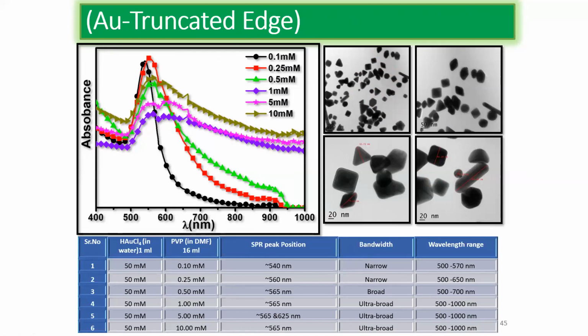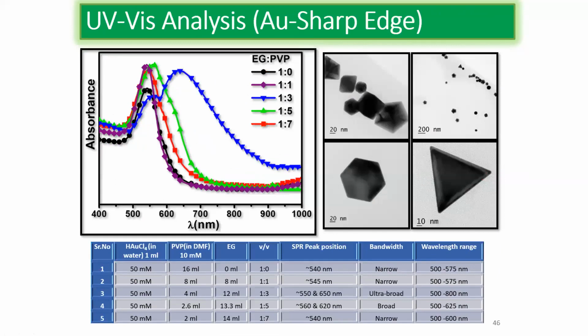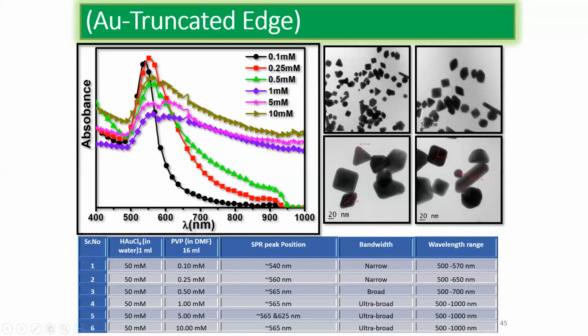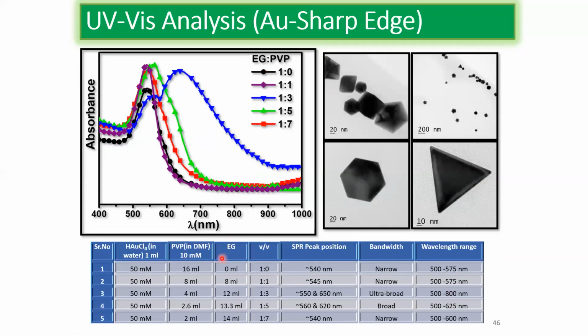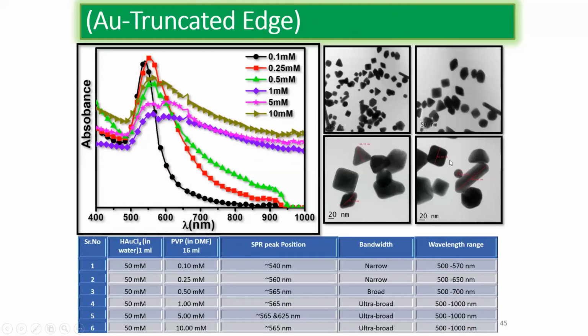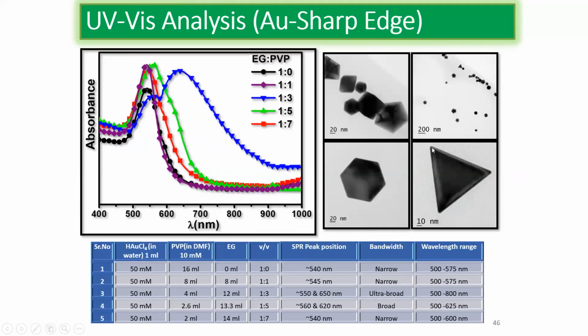So let us see whether this material is applicable in the solar cell also. In this, by changing the procedure a little, instead of PVP and DMF, I added some ethylene glycol. So this is like a two reducing agent type of system. And what I observed is that I could tune the corners of the material. In the previous one, it is a truncated edge type of nanoparticle, not a sharp edge. And this is a very sharp edge nanoparticle.